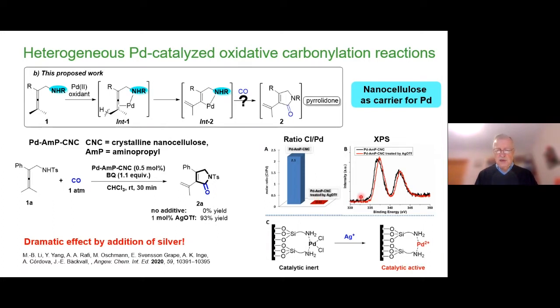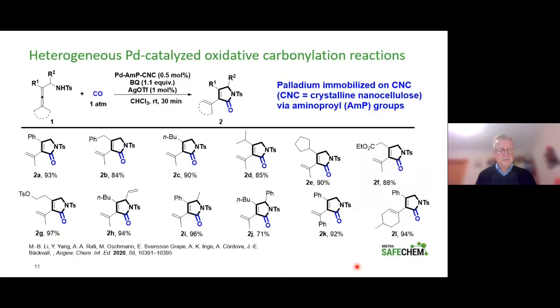And also interesting, we can see that the XPS changes a little bit. The red is after additional silver, and the black is before additional silver. And we believe that what is happening is the following: we know that silver chloride forms very strong bonds and falls out as a precipitate, and we get this cationic catalyst, which is the active catalyst.